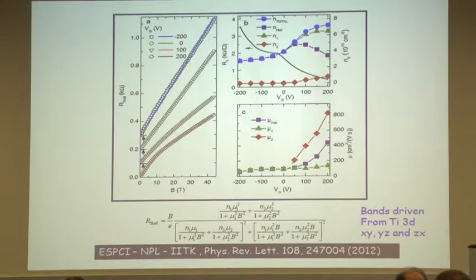Now we have done measurements of Hall coefficient and magnetoresistance up to very high magnetic fields, something like 45 to 50 Tesla. These experiments were done in Toulouse in France, again done by Jerome and his students. And what you see here is if I am at minus 200 gate voltage, I have a perfectly linear Hall resistance, almost a free electron-like behavior. But if I make the gate voltage positive, positive 200, I start seeing this curvature. But I've reversed the field, there is no hysteresis.